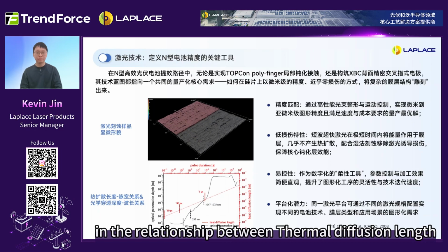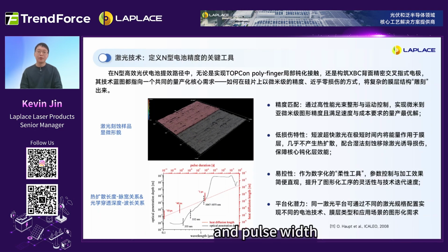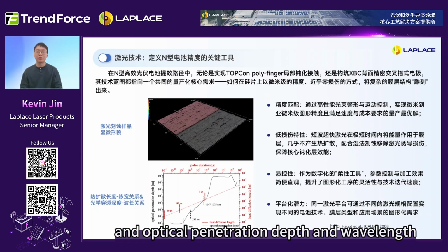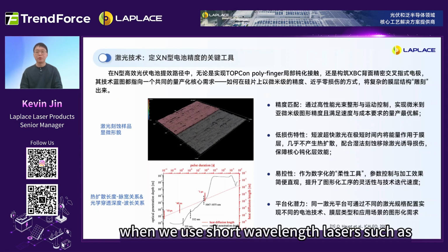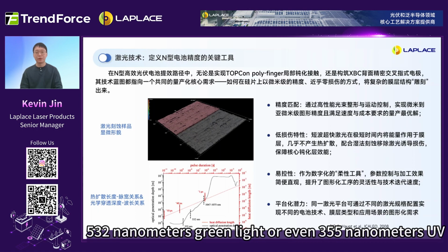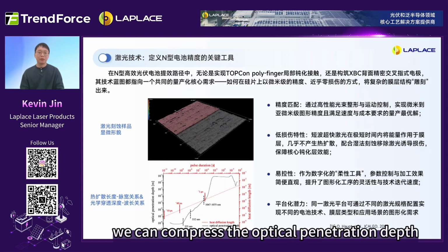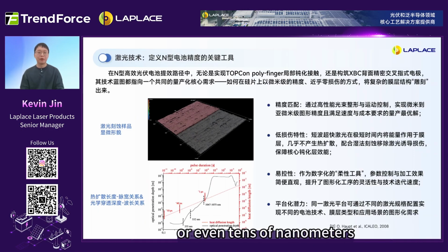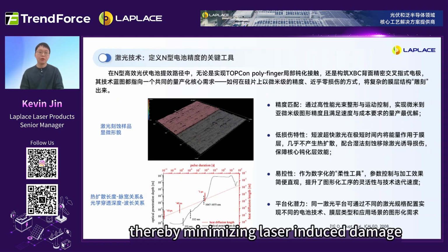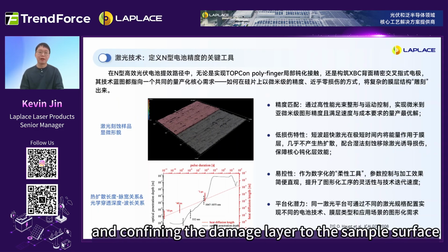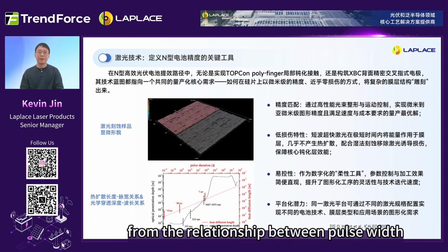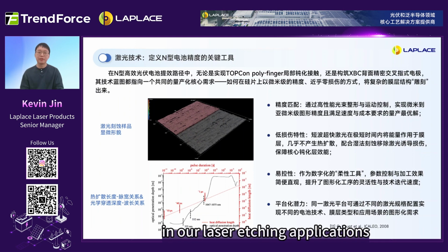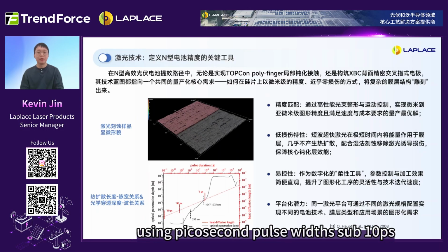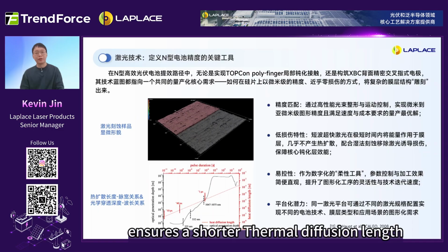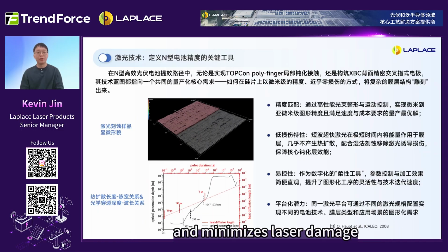This can be seen in the relationship between thermal diffusion length and pulse width, and optical penetration depth and wavelength in the charts below. When we use short wavelength lasers, such as 532 nanometers, green light, or even 355 nanometers UV, we can compress the optical penetration depth to within a few microns or even tens of nanometers, thereby minimizing laser-induced damage and confining the damage layer to the sample surface. From the relationship between pulse width and thermal diffusion length, in our laser etching applications, using picosecond pulse widths sub 10 ps ensures a shorter thermal diffusion length and minimizes laser damage.